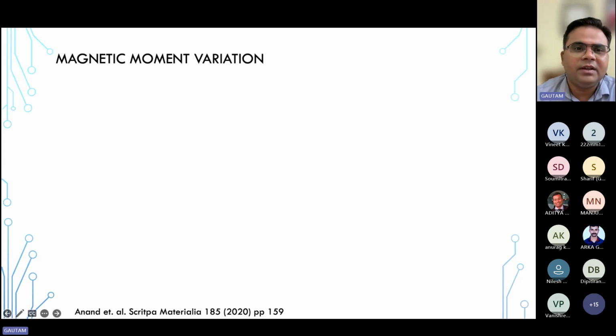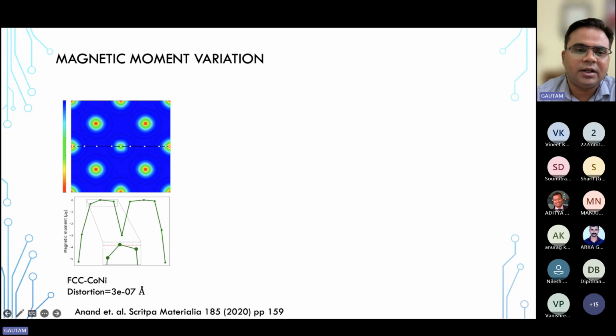So we studied why that might be happening. As you can see here in the context of FCC cobalt nickel, where we don't see any distortion, if you scan from one end to the other, between an impurity atom and a matrix atom, what you find is not a very significant magnetic moment fluctuation there.